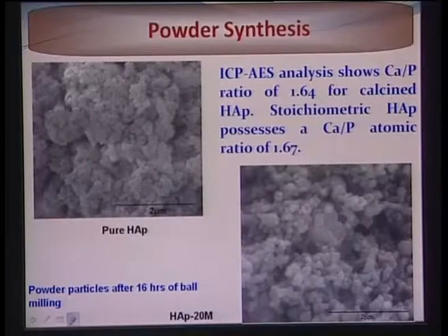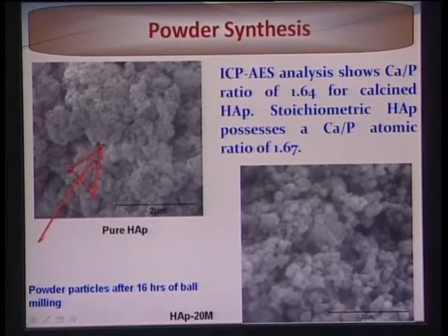Now, some of the experiments that were carried out to improve the hydroxyapatite toughness were to add mullite to hydroxyapatite. Now, this is the as-synthesized hydroxyapatite surface. If you look at this part, this is 2 micron here. Therefore, the individual particles here, which are largely spherical in nature, are certainly in the nano size range of 100 nanometer, or a little bit higher or lower than 100 nanometer.